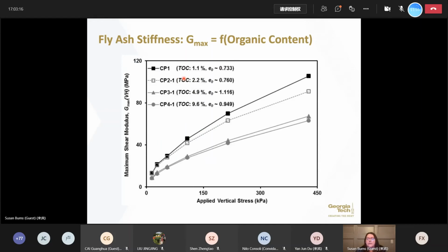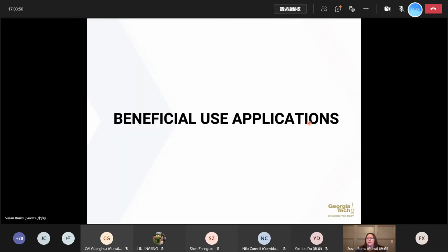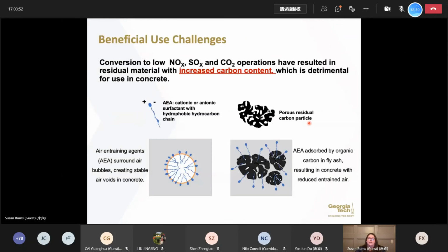In addition to that, when we start to look at some of the engineering properties of these ashes, like stiffness, for example, we're looking at small strain stiffness. As we increase our total organic carbon contents, we start here at about 1% and increase to roughly 10%, you can see that we'll have a decrease in our stiffness. These particles are very brittle, and so that makes sense, right? As we increase the number of those particles that are present, or the mass percentage, we'll see changes in these engineering properties. Ultimately, at the end of the day, though, we want to use these materials beneficially.